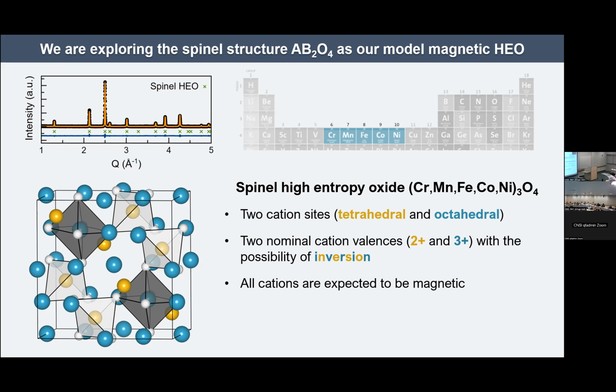Maybe you'll get to this, but with the spinels, they're often susceptible to distortions. So you have these super structures like the 3,4,13 or multi-unit cell structures. Do you see any of that? Yeah, no, we don't see any structural distortions down to 2 Kelvin, but I'll show you shortly, there's local distortions galore. Right, and the ones that I'm mentioning, you don't see distortions of the unit cell per se, but the coordination polyhedra are tilted such that the unit cell may stay the same, but the symmetry differs. Yeah, so these materials at a local length scale are different everywhere. Every coordination polyhedra is different from every single other one.